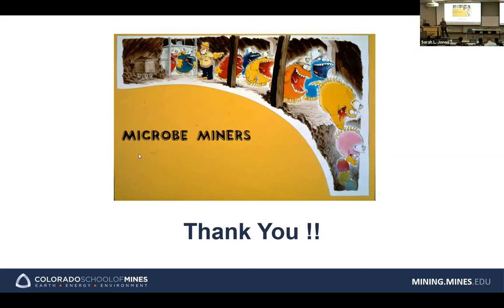So for heap leaching low-grade material, there's a definite advantage of bioleaching. If you have a sulfide and low grade, bioleaching has an advantage. But let's say you have copper concentrate, and you need to send the material to the smelter. The smelter can process, I don't know how many tons, a huge amount of material can be processed in a smelter, but biooxidation is a little slower, right?